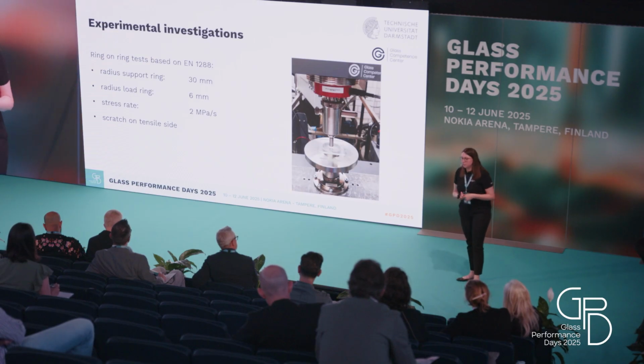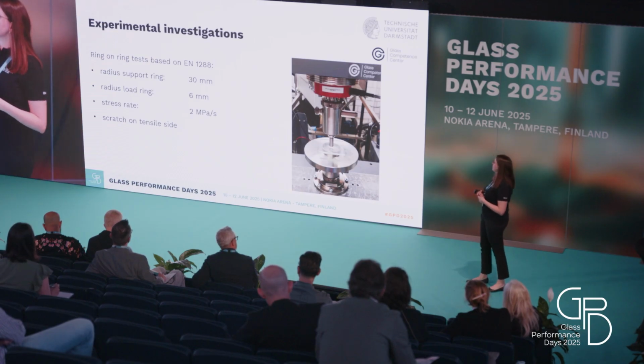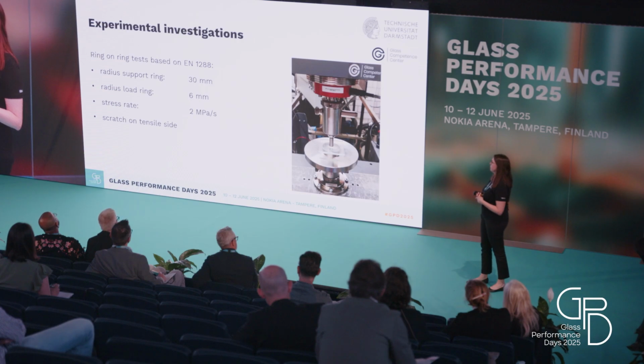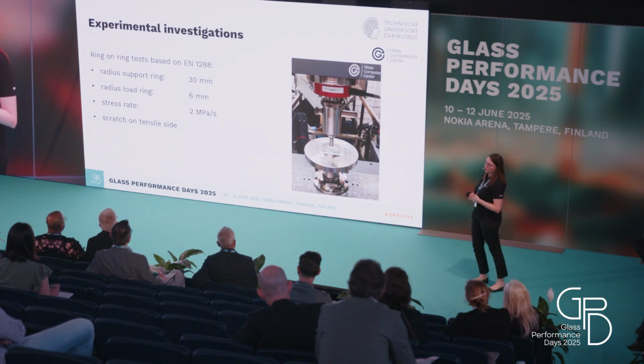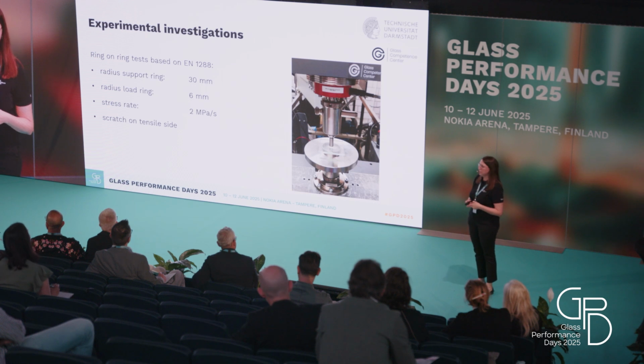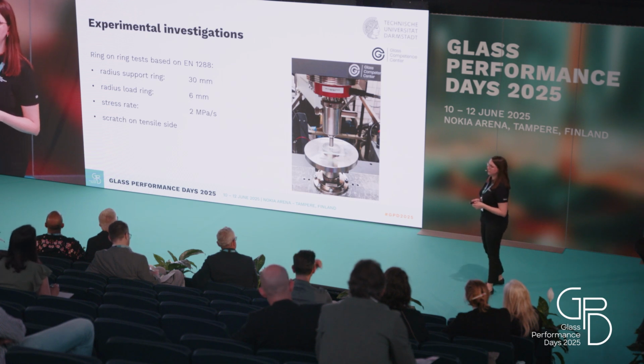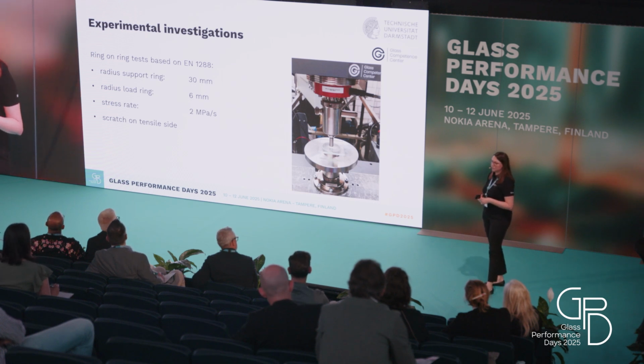After the heat treatment, we performed the ring-on-ring tests based on EN 1288. The radius of the support ring was 30 millimeters, the one of the loading ring 6 millimeters. We had a stress rate of 2 megapascal per second, and the scratch, of course, was always on the tensile side.